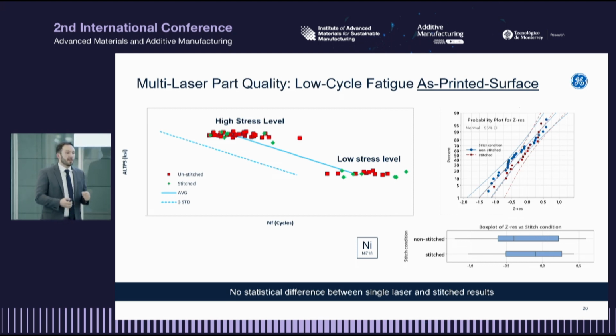So this was a shear overlap style investigation, so those types of offsets and mismatch that we had mentioned. This is a shear overlap. And we printed with a single laser what you're seeing in the red. They're horizontal fatigue specimens. You can get that stitch right down the center of it, and you're leaving the surface intact. So what we were missing from tensile before, we are now adding.